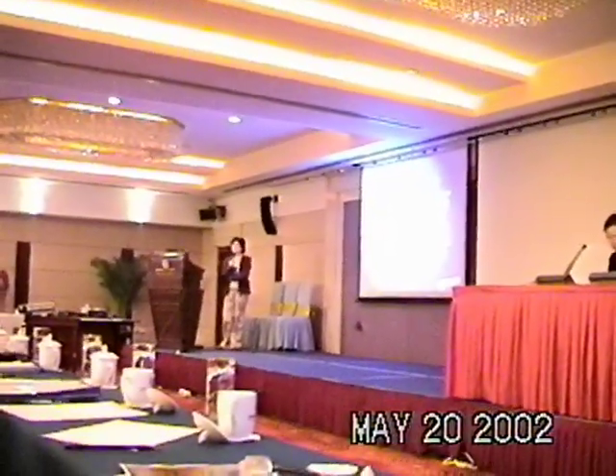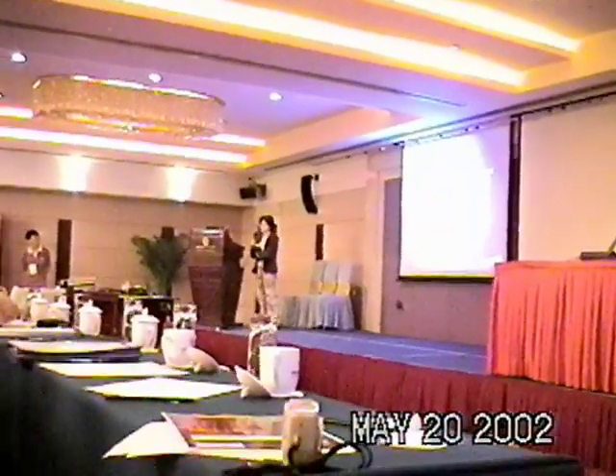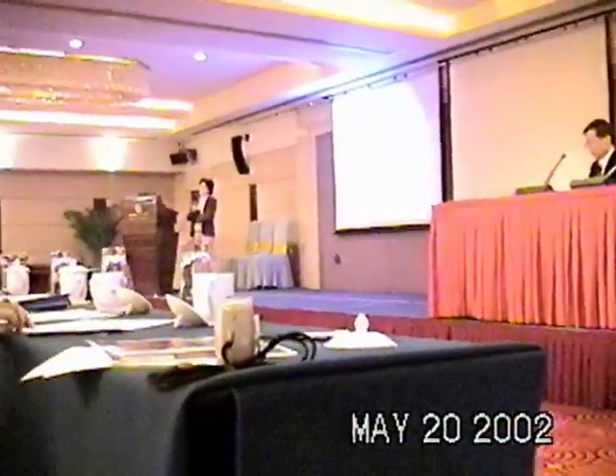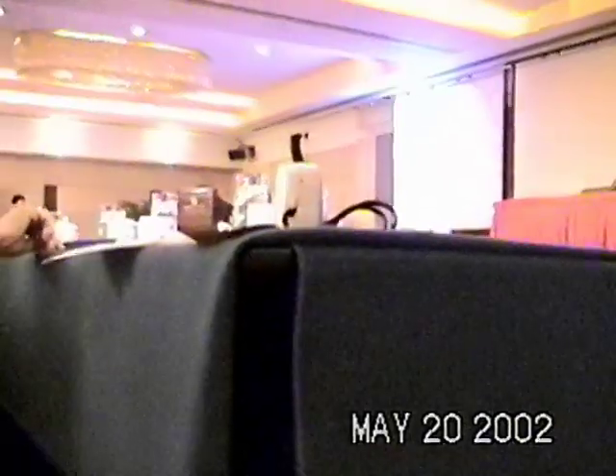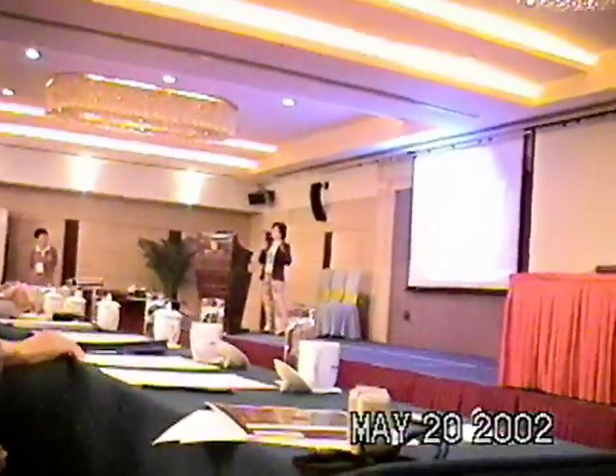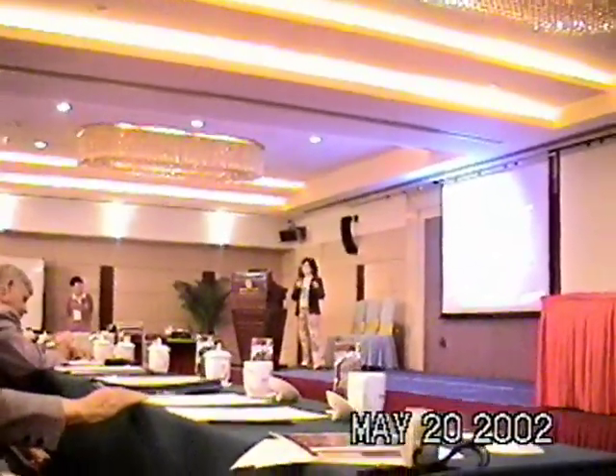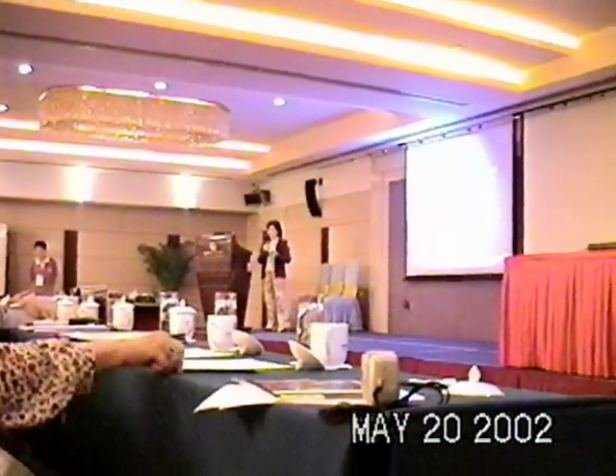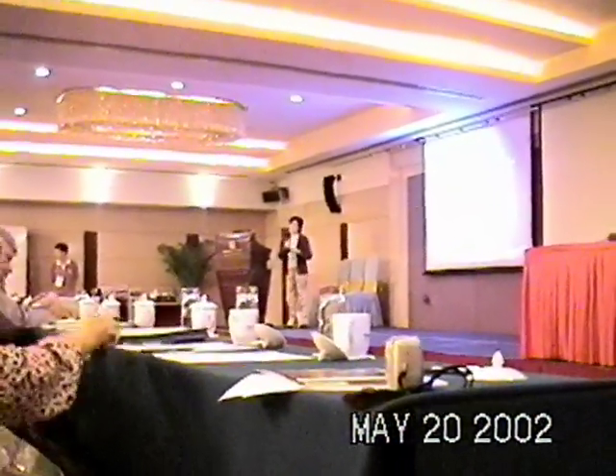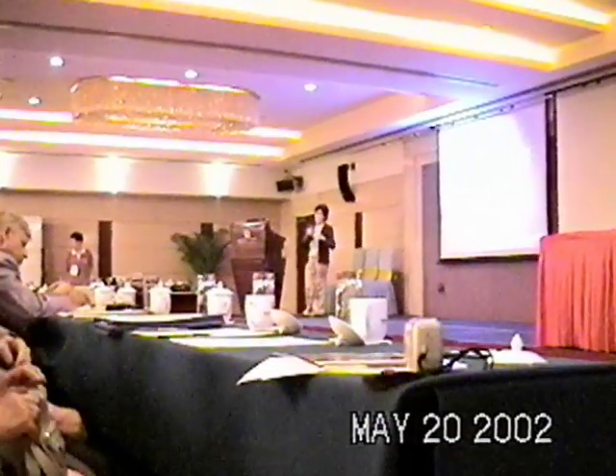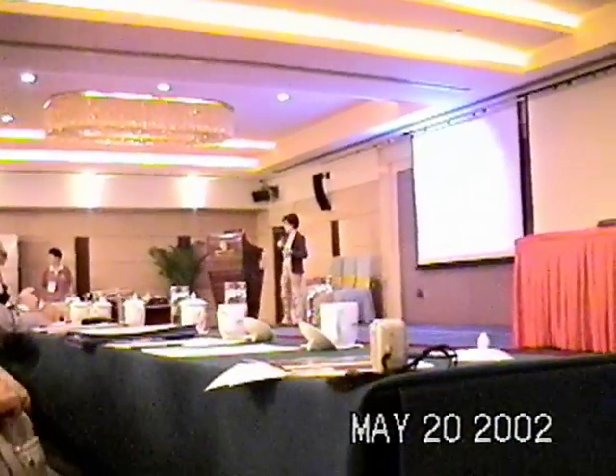We set up an experiment in which it's possible to measure helium every half an hour, 40 minutes. It depends on the dynamics of the experiment, but it is important that we are able to check if there is helium production during the experiment, and not to have only the integral amount of helium produced at the end of the experiment.